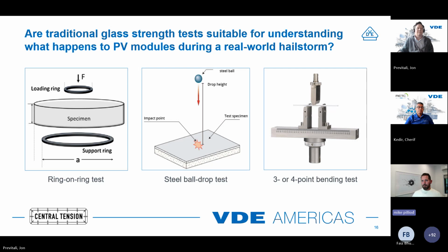All this being said, glass testing in general, or the probability of failure of a glass, does not have a standard. If you look at a data sheet, the strength of glass has a probability of failure. So you need to test enough populations because the flaw distribution in the glass is different from one piece of glass to the other. So when it breaks and how it breaks might be different in the same population, the same exact type of glass, the same processing, but those rate limiting flaws are different within it. So you need to do a certain population.